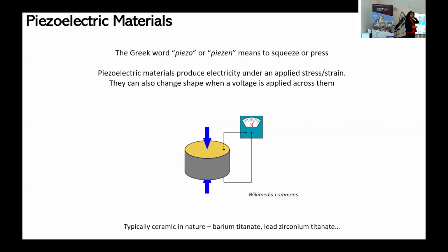So most piezoelectrics you come across, maybe barium titanate, lead zirconium titanate. So lots of oxides which show this effect. And I guess the important thing to note is, you need a non-centrosymmetric crystal structure for this to work. You need to have a dipole somewhere present in your structure, which when you then try to move apart or squeeze together, will change the polarization, which is then what produces this voltage across the material. So the existence of a dipole is very necessary.